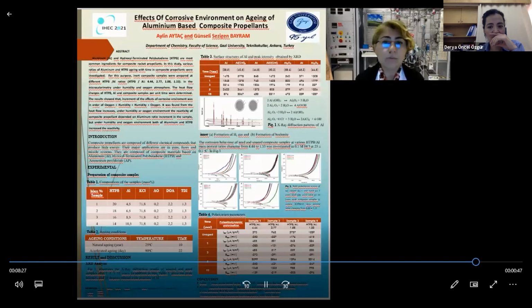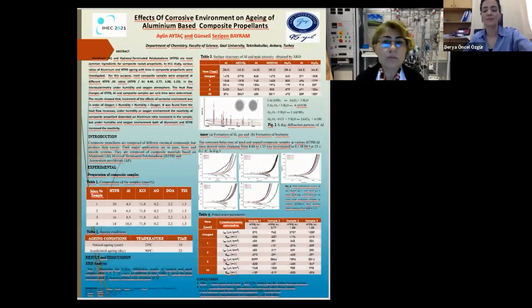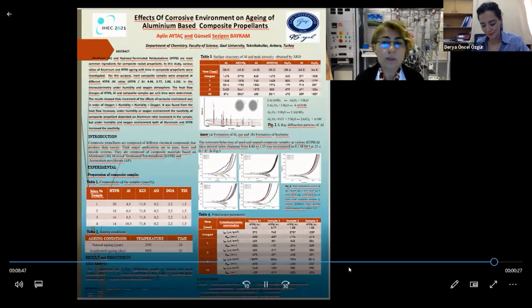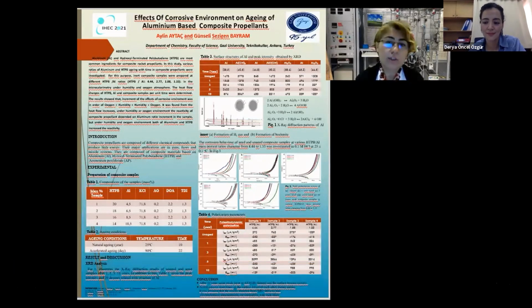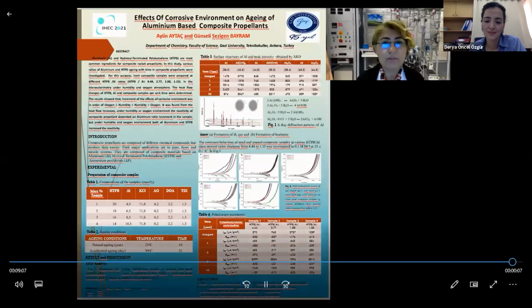After 1 and 3 years, these forms were determined by XRD analysis. Due to the oxide layer, the surface was still passive. After 10 years, again, there was an oxide layer in the aluminum oxyhydroxide form, and the surface became passive. Active-passive transitions on the surface followed each other during the aging. It was revealed that the results obtained from the XRD analysis and the electrochemical measurements are compatible with each other. Thank you very much.